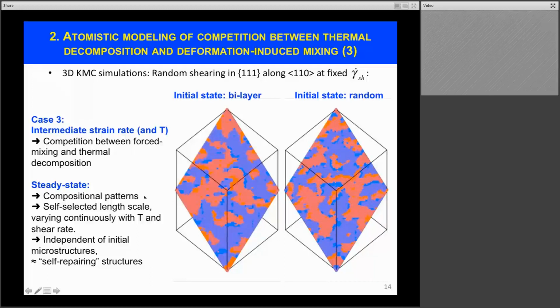so we refer to them as compositional patterns. What we observed here is that this system has self-selected the length scale of this phase coexistence. And if we were to vary the strain rate or the temperature, we can continuously tune or change the length scale of these nanocomposites. And so in this particular case, the steady states are independent of the initial microstructure. This is what we have just seen by watching these two movies.